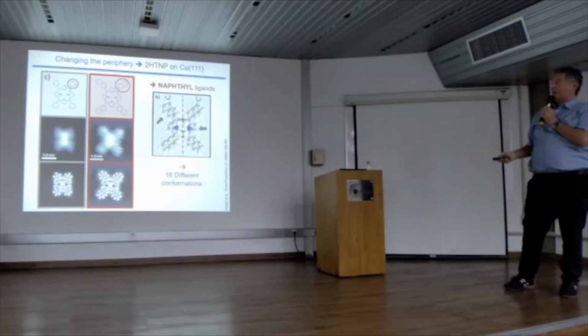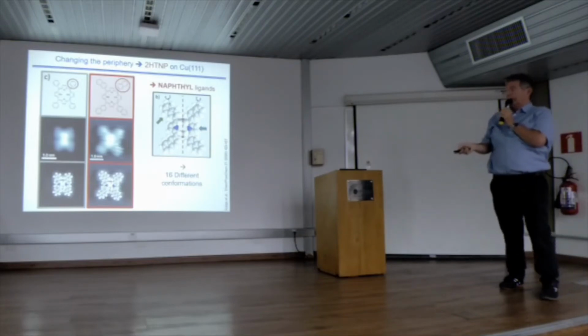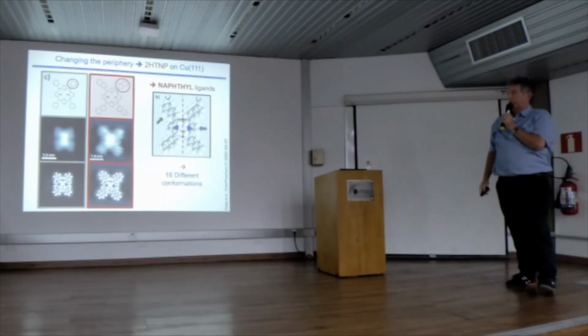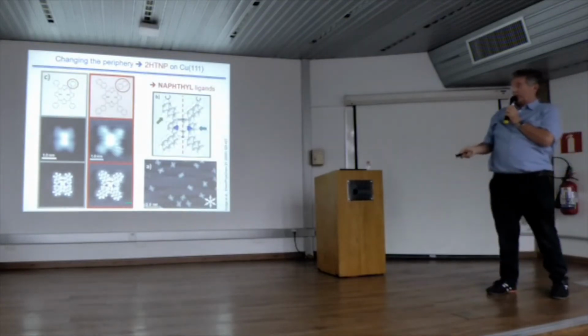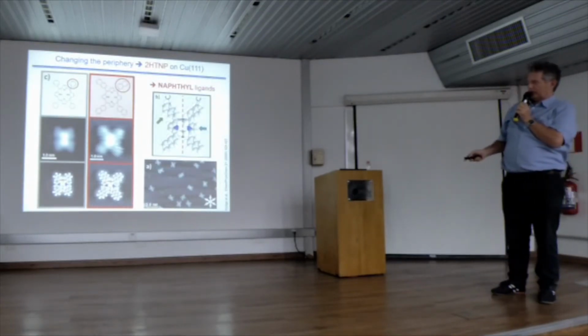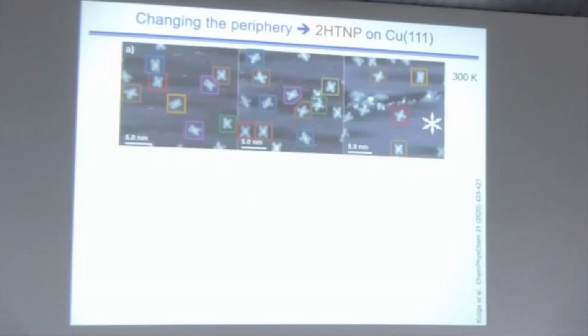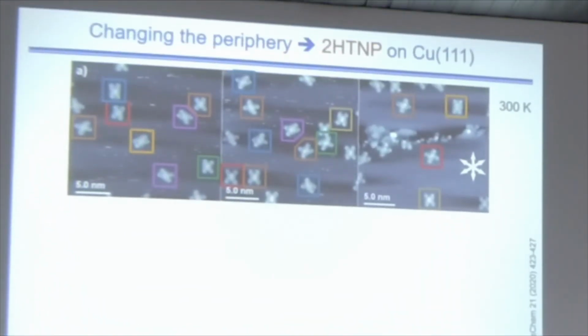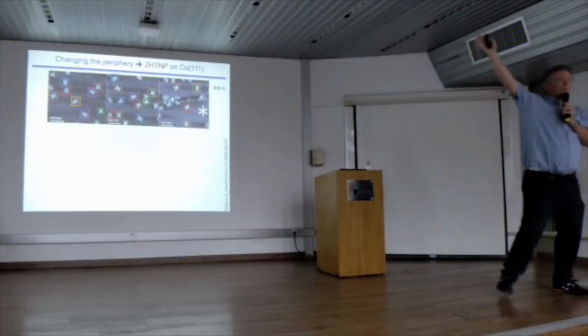And you have two species. Each you can rotate, so you have 16 different conformations that are possible. And then we measured on the surface, and indeed we found, if you look at this one, this looks pretty large, and this one looks pretty slim. And then we looked much more carefully, and here I added 3 images and color-coded different shapes. So if you look at this shape, this is this guy. And if you look, for instance, at this one that looks like a K, this is this guy.